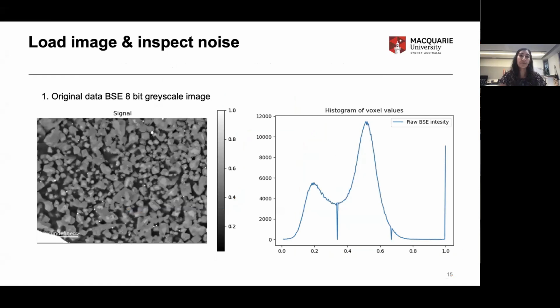I'm just going to talk through how this workflow actually runs so that you get a flavor for what we're doing in the background and you can have an appreciation for how we've tried to improve grain size measurements. So all of my images were 8-bit grayscale images from a field emission SEM. They were initially fairly high quality images, but this method also works really well on tungsten SEM images as well. So you don't need to have extremely high quality initial grayscale images. The first thing to do with the workflow is to load in your original 8-bit image. And from there, you can see that we generate a histogram showing the inherent grayscale noise. And this will be present in all images.